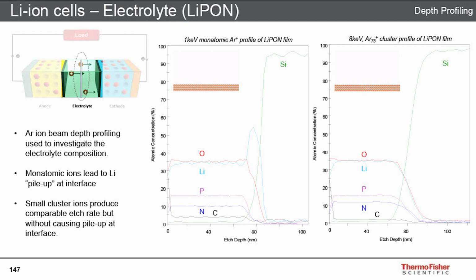You can also see the actual amount of lithium we measured throughout. It's not a huge difference, but we're just below 35% along here, and we're exactly on 35% here. So that small variation in the lithium concentration is that lithium pushing through the film as we sputter with the monatomic ion and coming to the surface here. You see the same kind of thing with sodium as well and other alkali metals. They're quite mobile under ion bombardment. So if you're looking at samples like glass, you do have to be quite careful with milling through them.